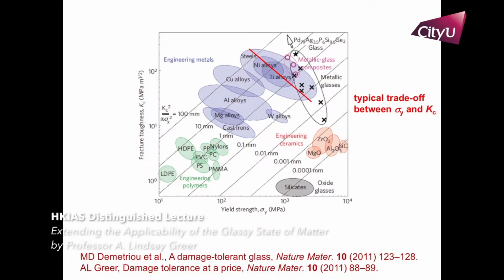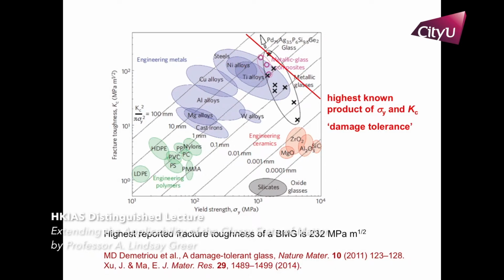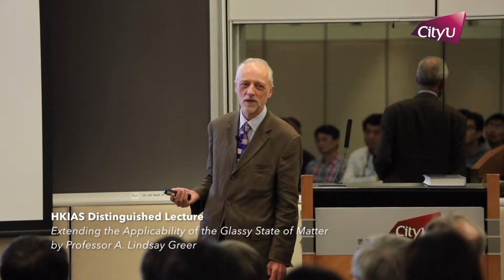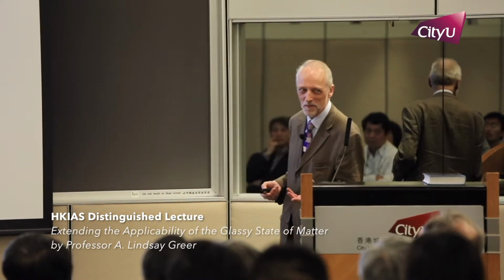Well, the X's are metallic glasses. The circles show you some metallic glasses with crystals inside. But the very best point is this one. And it's quite interesting that not only does that have a rather high value of this product, which you could call damage tolerance, but it's the world record value. It beats any other material.